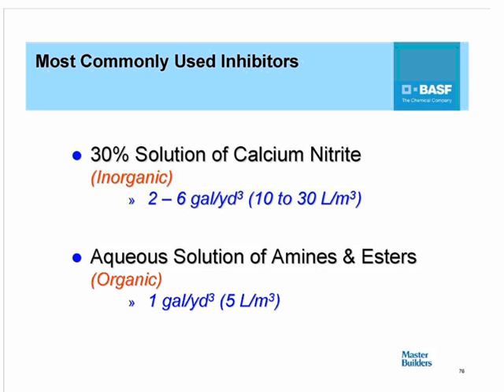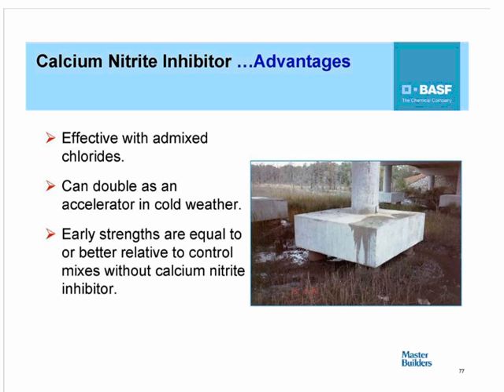The calcium nitrite, which is inorganic in nature, is typically used at dosages ranging from about 2 to 6 gallons per cubic yard. In most applications, such as parking garages, anywhere from about 3 to 4 gallons is typical. In marine applications, then you get into the higher dosages of around 5 gallons per cubic yard. The aqueous solution of amines and fatty acid esters is typically used at an optimized dosage of 1 gallon per cubic yard.